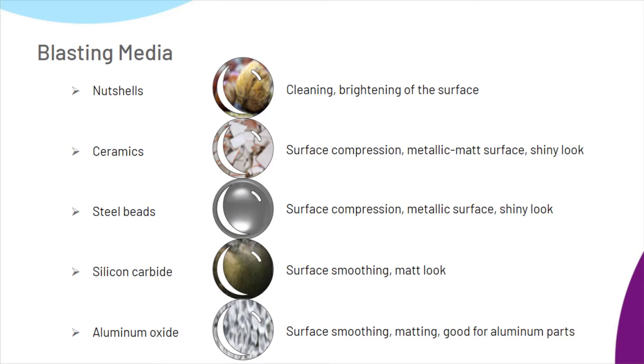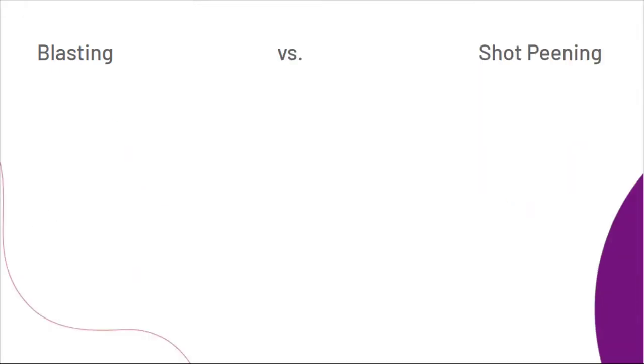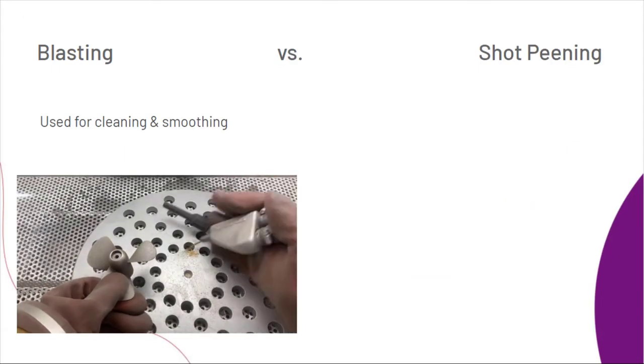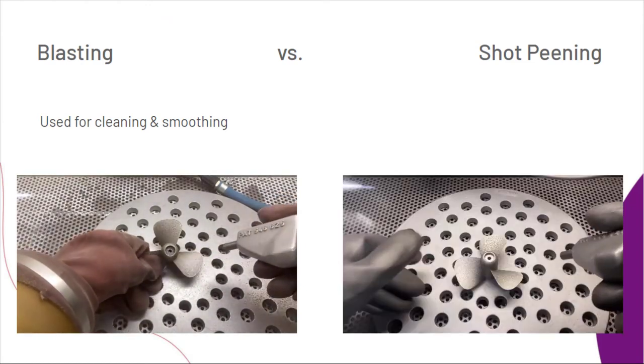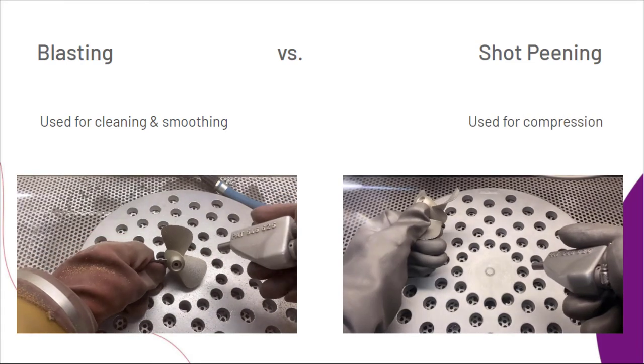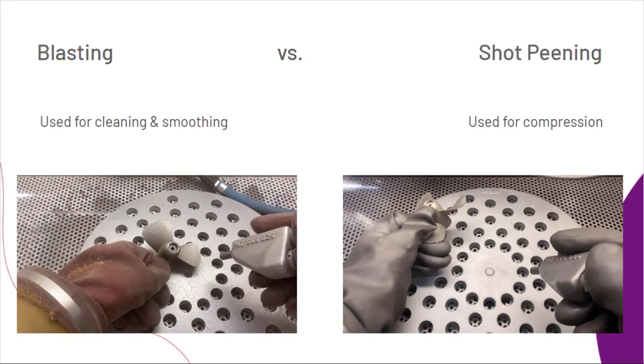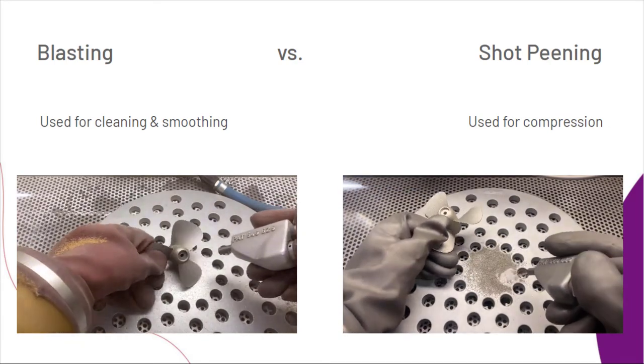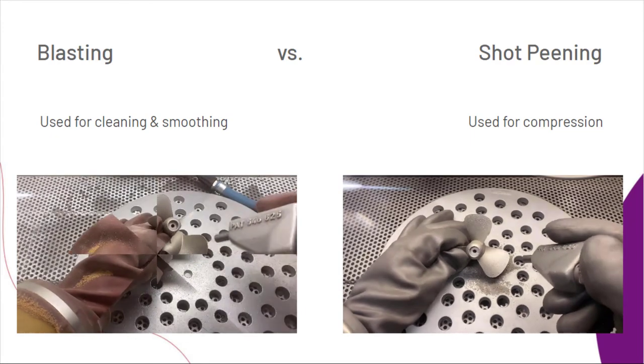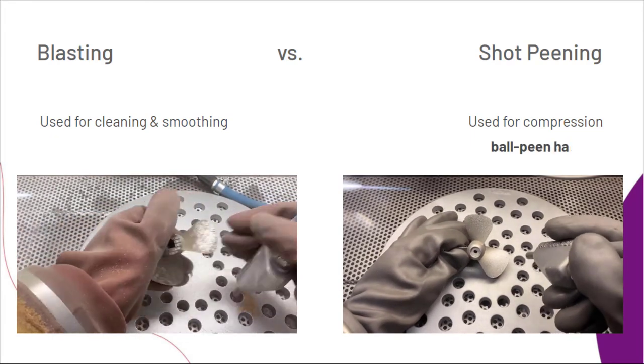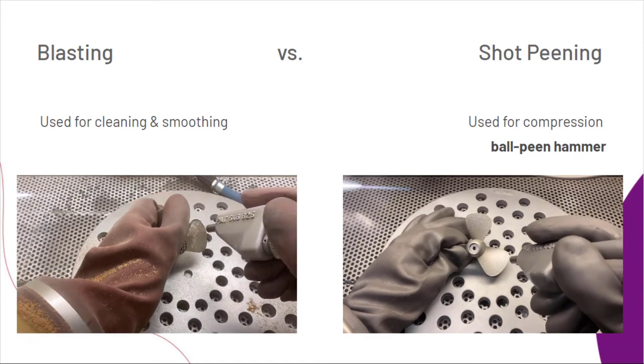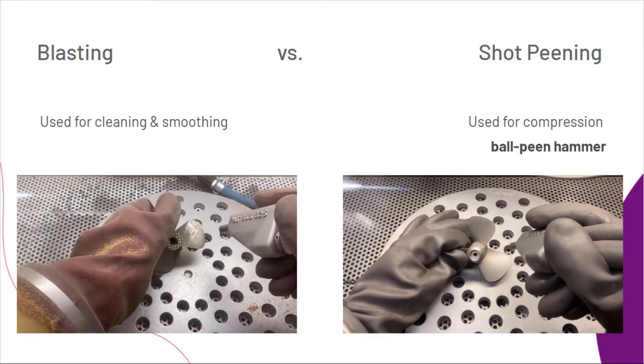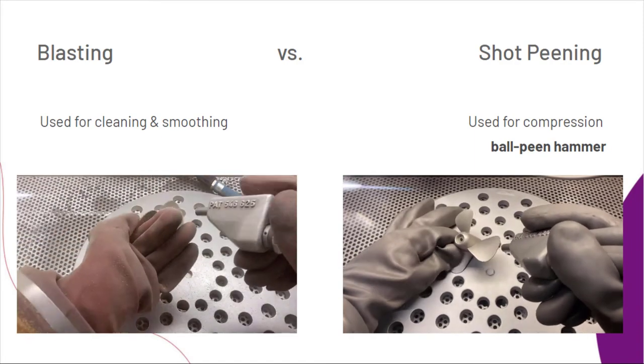Aluminum oxide is often used for aluminum parts and is suitable for smoothing; the result is a matte surface finish. Whereas blasting is mainly used for cleaning and smoothing, shot peening is used to produce a compressed layer in order to change the material properties. The surface or roughness profile is compressed due to high-speed particles which act as a ball peen hammer. Compared to blasting, shot peening uses higher pressure and thus energy to compress the surface of the material.